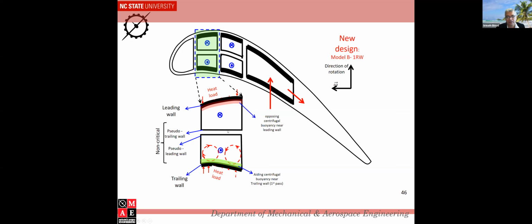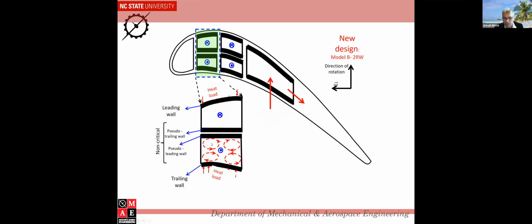What it does is it changes the flow structures, especially the rotational effects of Coriolis force and centrifugal buoyancy and all this stuff. As you can see, the red are the major structures. The blue is when you add centrifugal buoyancy to the surfaces, and then you can see the effect on heat transfer. Now suddenly, when you see the new channel, there are 4 vortices that have been created instead of 2 vortices. You also see that centrifugal buoyancy actually stabilizes the flow and enhances the heat transfer more evenly.